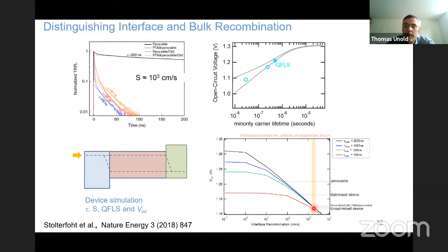We can read off the interface recombination from this plot. It was something like 10 to the 3. That's what I've shown you up here. And now the question is, does it help, if you have such strong interface recombination, to have a longer lifetime in the bulk? It shows you very directly and very clearly, it doesn't matter at all. All these curves fall on top of each other. It would only matter if the interface recombination is small, let's say at least smaller than 100 or 10, then it really helps. If you increase your bulk lifetime, then it would help the VOC of your device.